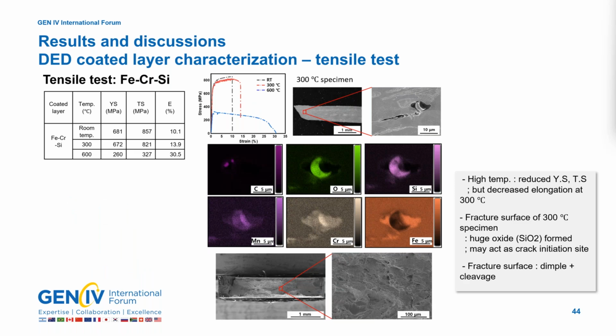The fracture surface of the 300°C specimen of the iron chrome silicon coated layer was also examined. Similarly, large silicon oxides were observed, which also acted as crack initiation sites, leading to a reduction of elongation.